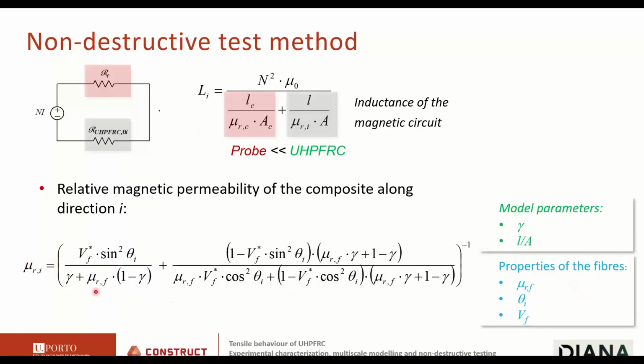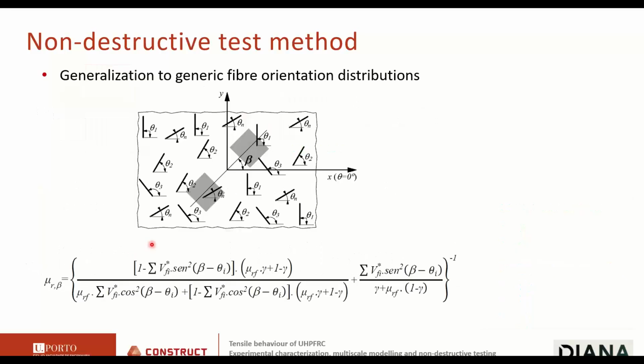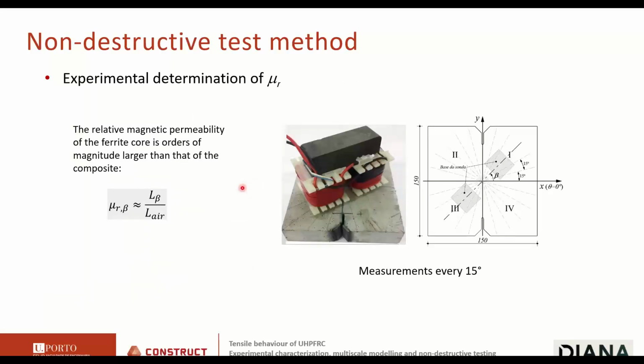So we found this very ugly equation, but you can put it in an Excel spreadsheet, and it basically provides you the relative magnetic permeability as a function of the fiber content and orientation of the fibers. Of course, our fibers can have random orientations. We can generalize this concept to the cases where you have fibers with different orientations. So let's see how this compares to experimental evidence.